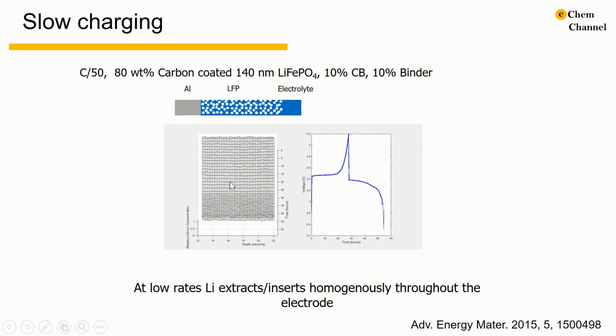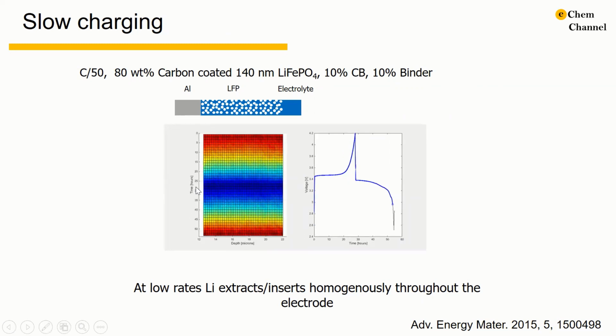lithium ion concentration increases. Then, the lithium ion concentration is plotted as a function of time and depth in the curve. Red means high lithium concentration and blue means low concentration. Over the electrode depth, the change of the lithium ion concentration is even or almost depth independent. It means that all grains charge and discharge at the same time.